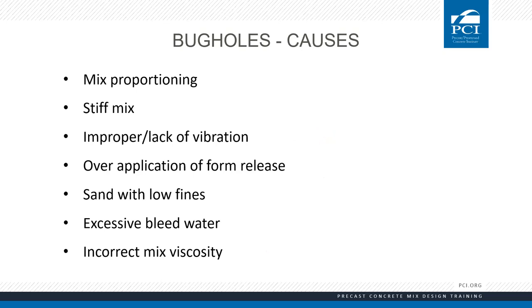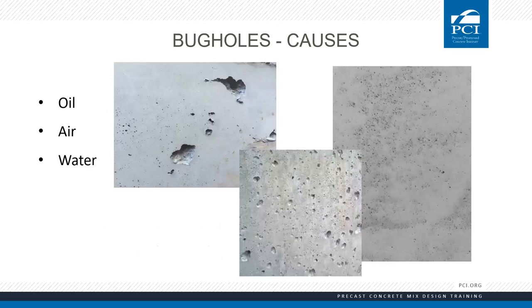Let's focus on bug holes. What are some causes? A poorly proportioned mix, a stiff mix, improper or lack of vibration if the mix is intended to be vibrated — though most SCCs are not. With SCC mixes, the more we vibrate or introduce dynamic energy, the more chances we'll have bug holes. This may be an internal or external vibrator, or even a truck driving across potholes in your yard. Anything that introduces dynamic energy into your concrete could potentially increase bug holes. Overly applied form oil will create bug holes, as will sands with very few fines, excessive bleed water, and incorrect viscosity.